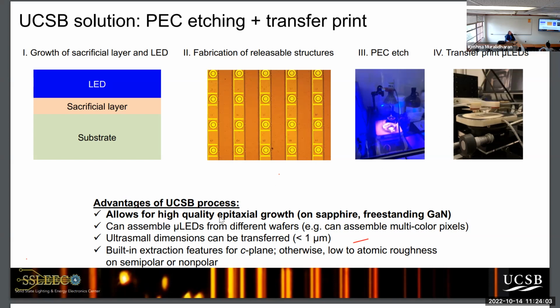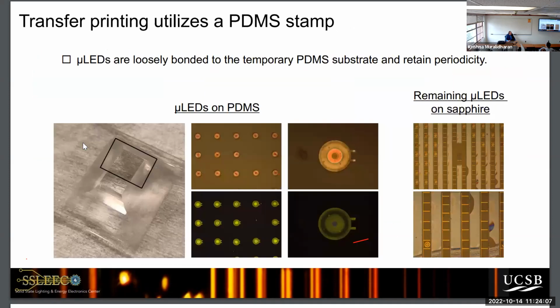So I'll show you what this looks like. This is what it looks like from the top. This is the side view. This is what it looks like. You literally just attach this PDMS stamp to the top of your device. And after you etch it, it pulls off all these micro LEDs. And then you take this stamp and you can stamp it on any kind of display you want. So this is the mass transfer approach.